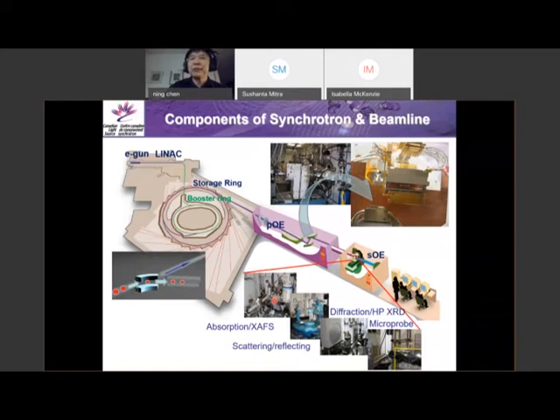The powder diffraction you are going to use at the Brockhouse beamline. In Brockhouse, you do the refinement, you get the fine structure. In the future, at HXMA, we still keep powder diffraction, but it will be in situ measurement in step with XAFS, and that will be for speciation. For example, you look at a specific 2-theta angle or diffraction peak, something like that. Anyway, that's the overall general information regarding synchrotron 101.